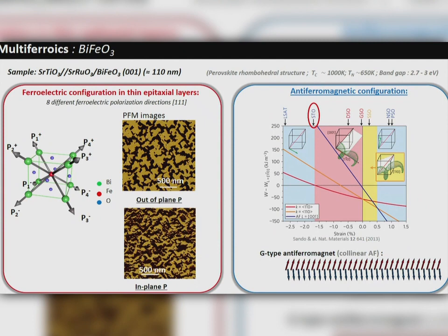It's typically a thin layer of 100 nanometers grown on the STO substrate. And what you can see here, again, these are PFM images, so the only thing you have to know is that basically they represent the ferroelectric domains. Here you can have the 8 possible variants like this, and these are quite small. And choosing the STO, we choose to be in the G-type kind of antiferromagnet, okay?